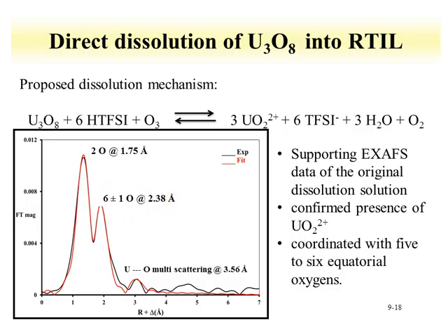So this shows that this reaction forms the oxidized UO2 in the TFSI solution, and that any chemistry at this point is done with the uranyl. One of the issues with the uranyl is that we have oxygen present on that molecule, so in reduction of this molecule on an electrode, we've shown that under certain conditions it can form uranium dioxide on the electrode surface.